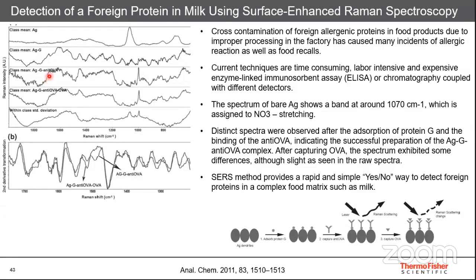Now, once this protein material has interacted with anti-OVA, that is the binding of anti-OVA, it has shown a spectrum, and when it has captured the OVA, it has resulted in a different spectrum. In the normal first order spectrum, the peaks are not that distinguishable. So you take a second derivative of your spectra, and now you can see the actual variation in the peaks. The peak which you see in silver anti-OVA disappears when the OVA is incorporated, and now you can see this peak has been enhanced.